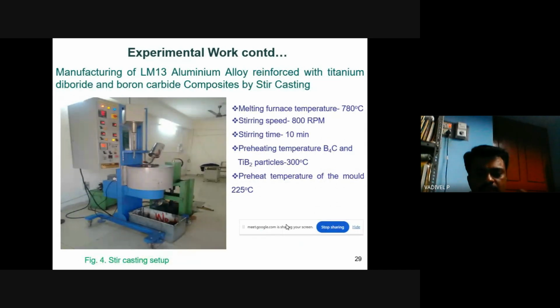So the picture you are seeing here is the stir casting machine. Okay, the melting furnace temperature is 780 degrees Celsius. The stirring speed is a maximum of 800 rpm. The stirring time is 10 minutes. And the preheating temperature of the ceramic particles is 300 degrees Celsius. The preheat temperature of the mold is 225 degrees Celsius. So this is the stir casting setup we have used for the experiment.